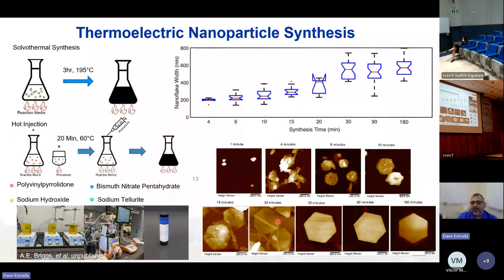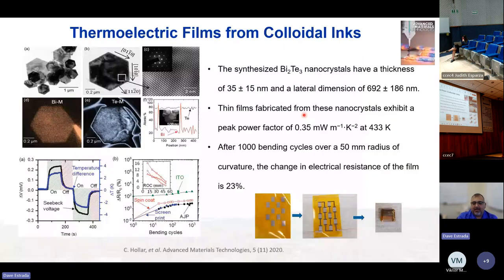And so their lateral size can range from about 300 to 700 nanometers, but that's still good for aerosol jet, maybe not for inkjet. And then here you can see the corresponding width over time as well. At about 20 minutes, we're getting an average of about 400 nanometers on the flake width. We didn't see much dependence on the thickness. They're all about 35 nanometers thick, so they're still good for aerosol jet and plasma jet printing.